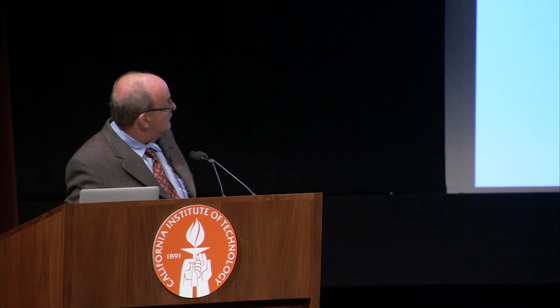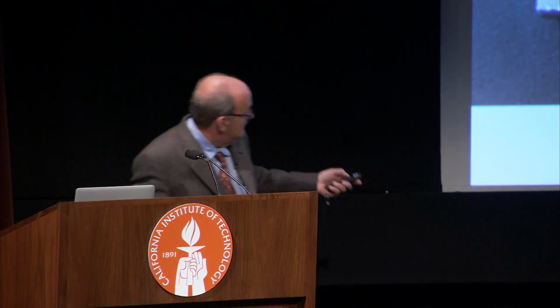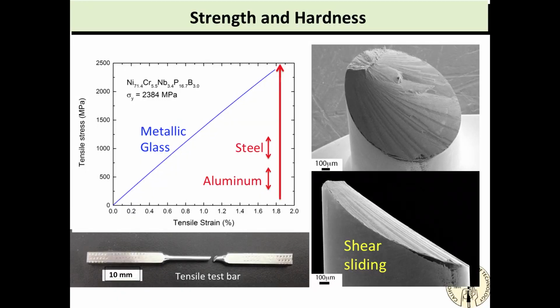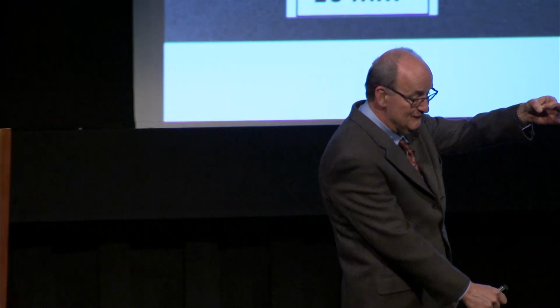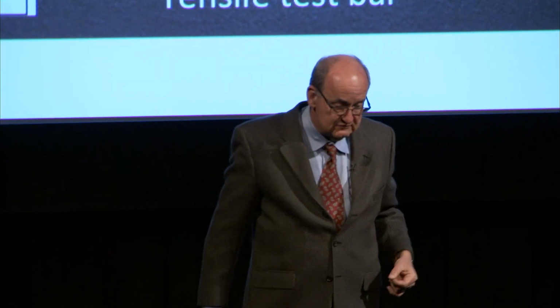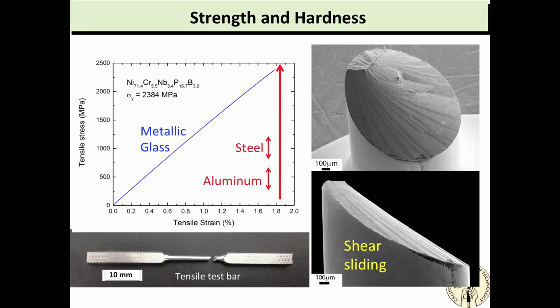Okay, so just to show you, if you take a tensile bar and you pull it, these are some units, they're megapascals. That corresponds to about 400,000 pounds per square inch. So if I have a square inch bar, I could hang 400,000 pounds. I could hang 60 pickup trucks, right? That's normal metal. That's a high performance thing you make airplanes out of. It's about that strong. It's actually, I've overestimated. Aluminum's down here. We make airplanes out of that. That's steel. We make skyscrapers and bridges out of this. That's metallic glass. Okay?